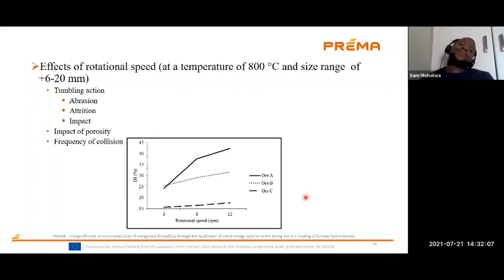Here's the discussion about the effect of rotational speed. As mentioned in the literature, the main factors that affect the decrepitation are the tumbling time and the tumbling action. Tumbling time in this case won't be focused on, since the tumbling residence was kept constant at 30 minutes for all the experiments. So we'll only be focusing on the tumbling action. We have abrasion, attrition, and impact, which are mostly responsible for causing the production of fines when the sample has been tumbled in the rotary kiln.